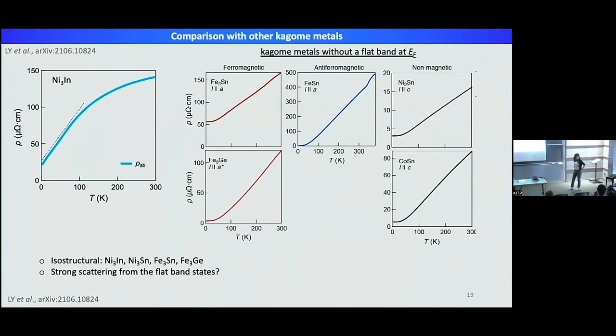Oh, okay, so in all of these compounds, you would say it's unconventional. Sorry, are you asking about the phonon resistivity curve from scattering between electrons and phonons? Well, I expect that at a temperature much greater than Debye, linear in T is expected from phonon-electron scattering, yes. And this is what's happening, I think, in the other systems, where above 50 Kelvin you have a T-linear resistivity that comes from phonons, right? And if the T-linear extends below T Debye, then I would think that's unconventional. What I'm showing on the left is unconventional because it extends below Debye, and on the right, it does not. So those are the conventional cases, and the left is the more unconventional case.